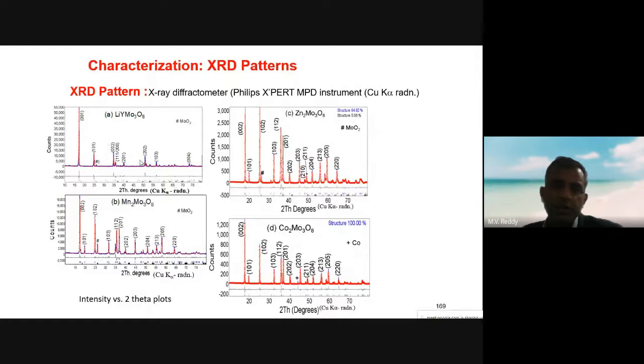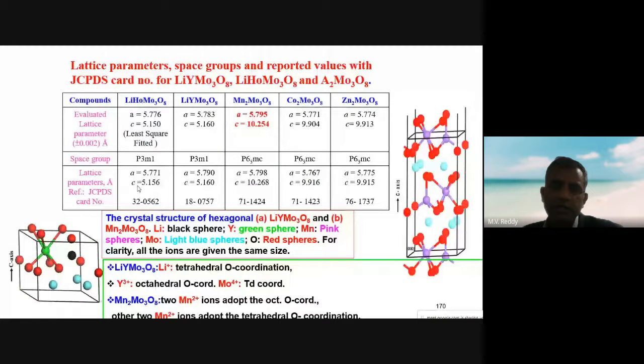You can see clearly these are the different lattice parameters we obtained for different types of compounds. For example, LiY, Mo3O8, whereas lithium holmium, Mo3O8, or sometimes manganese molybdate, their C value is expanded. That's why you can see that expansion with higher C value, as a consequence of the difference in the crystallographic representation.